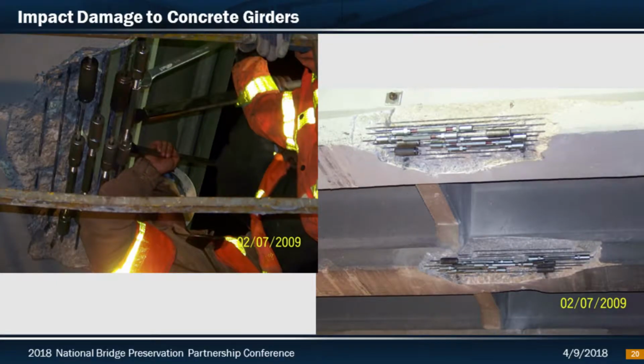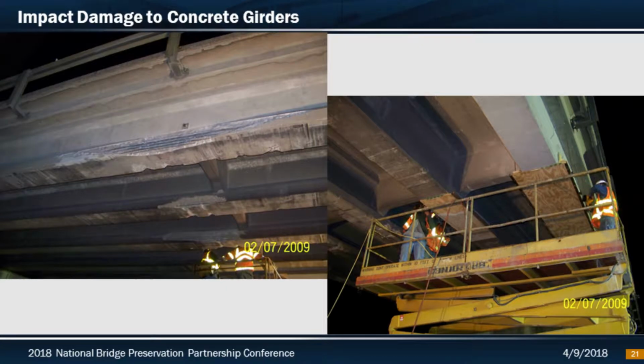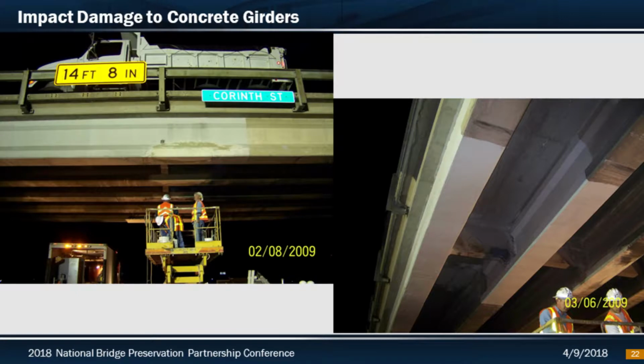They basically had the state forces come out and do the beam repairs, splice in a few strands, and do the patching of the concrete, repairing the existing concrete beams with the new patching material. There's where we had the 40 kip truck on top, which effectively preloads that beam and allows for that pre-compression. Once you remove that load after you've cured your concrete, you get a compressive action on your patching material.